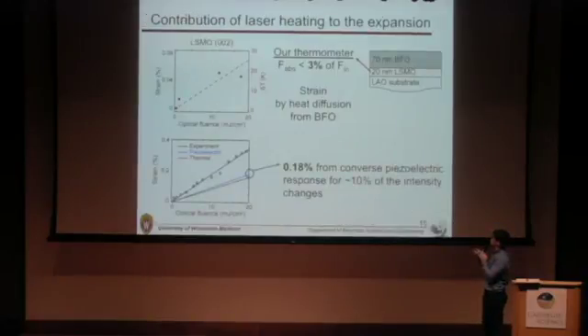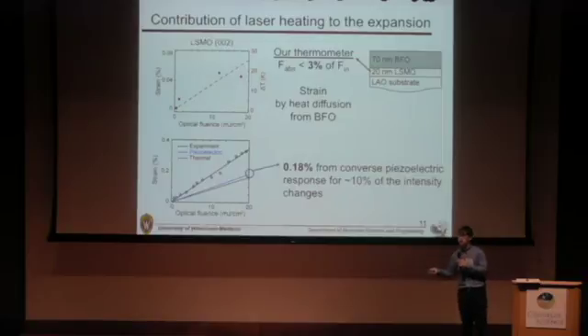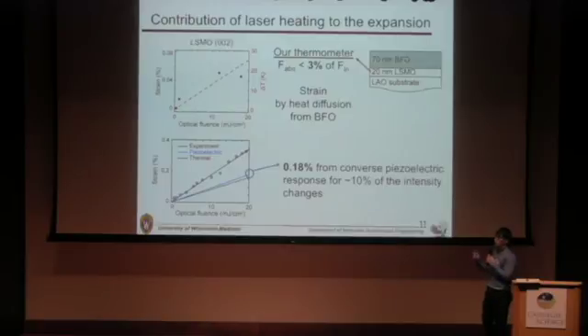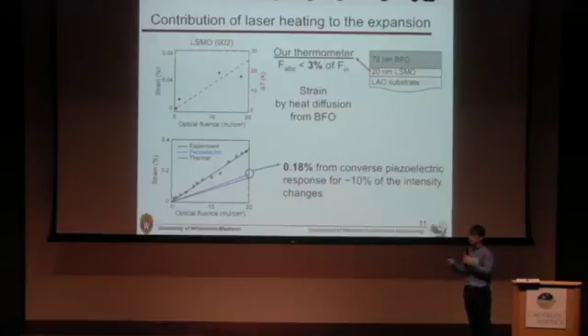So we test this by using the LSMO electrode at the bottom of the bismuth ferrite thin film. So we have seen the strain in the LSMO, and we think this arrives from the heat diffusion from the bismuth ferrite, because based on the calculation with the optical parameters of the bismuth ferrite and the LSMO, the absorbed fluence has to be less than 3% of the incident fluence, which means that the direct effect of the fluence on the LSMO has to be negligible.